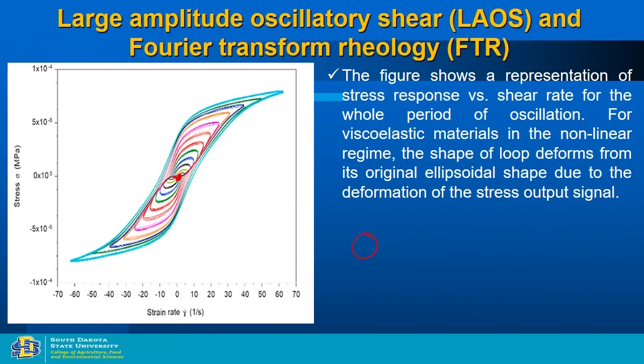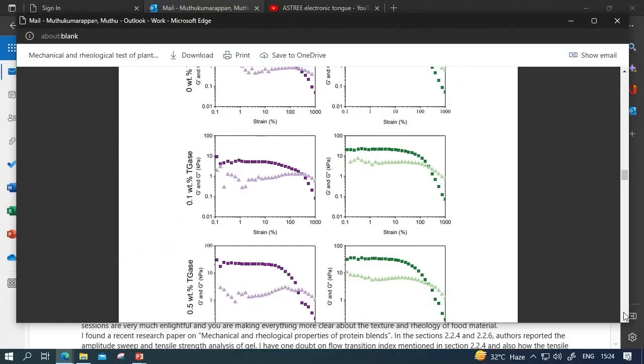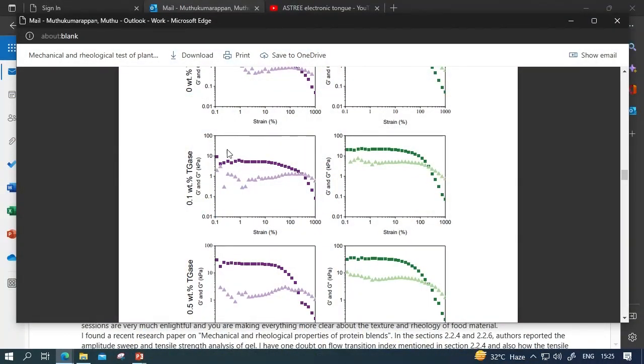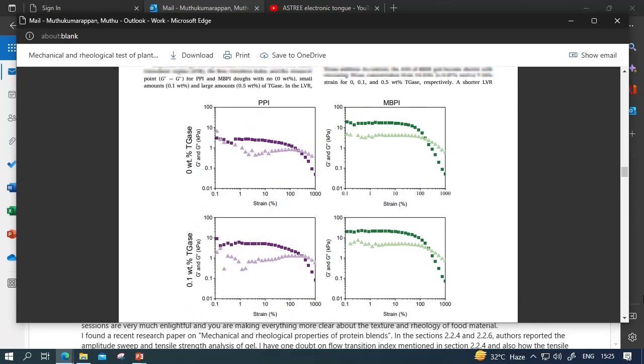Maybe I can explain to you a little more if I show you a result. So these are all the dynamic rheology tests these authors did, and you see G prime and G double prime as a function of strain. So it's in log scale. If you present this data in a table format, it's difficult to explain the whole process, what's happening. What they have done in this work is they have collected this data for the gels they developed, and